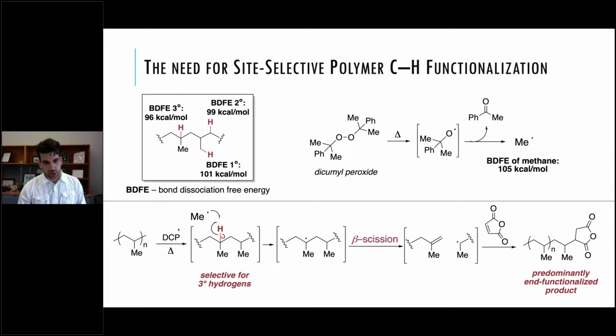This is just a mechanism, you don't have to pay attention to it. The problem here is this beta scission. This beta scission means that every time you try to add a functional group to polypropylene, you're actually breaking that polymer chain in half. And if you do that a few times, that polymer becomes an oligomer, and those oligomers don't entangle and don't have good properties anymore. So this has been the fundamental challenge for recycling polypropylene since the 60s: every time you try to do anything to polypropylene, it falls apart.